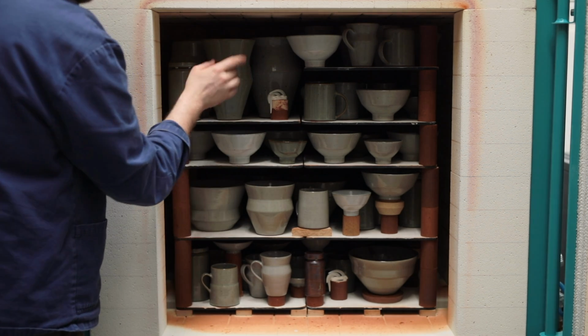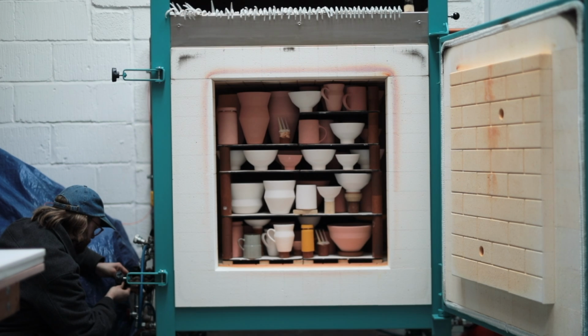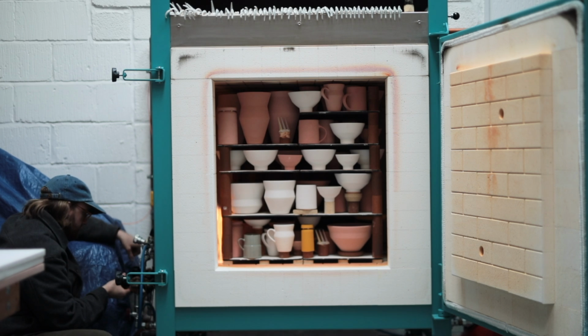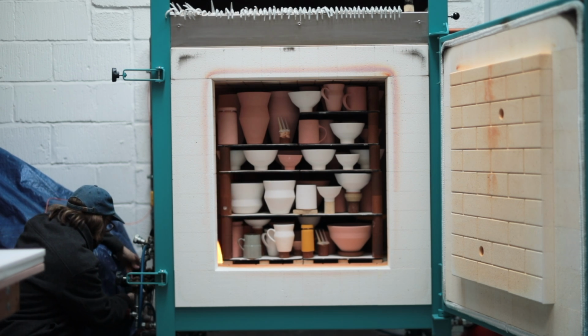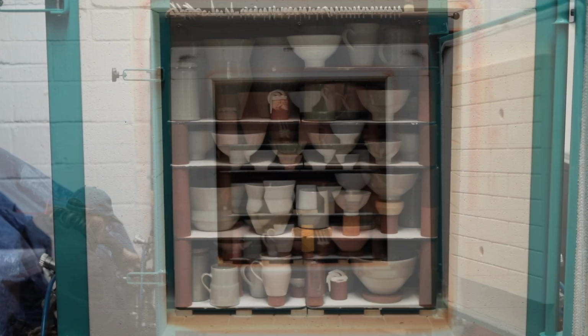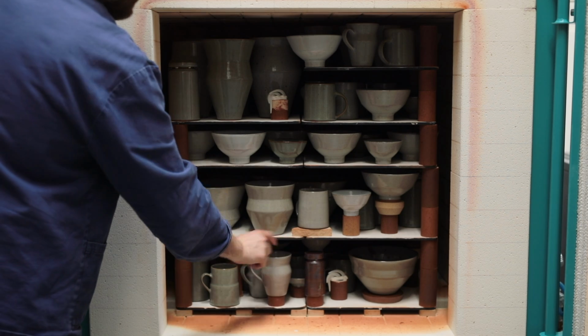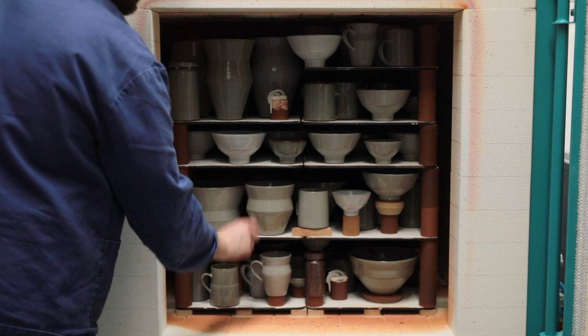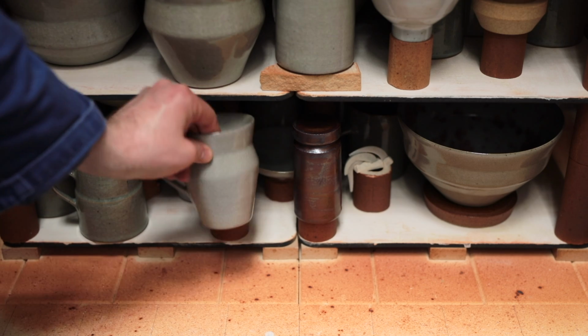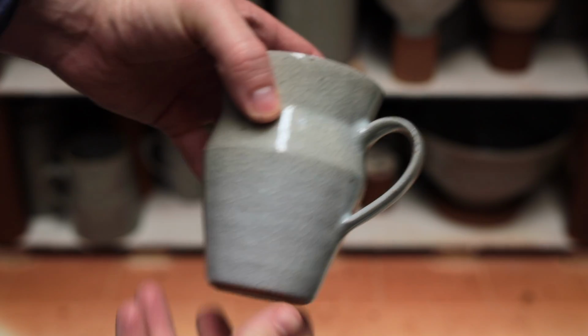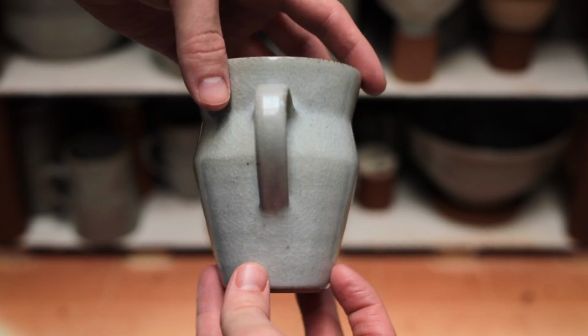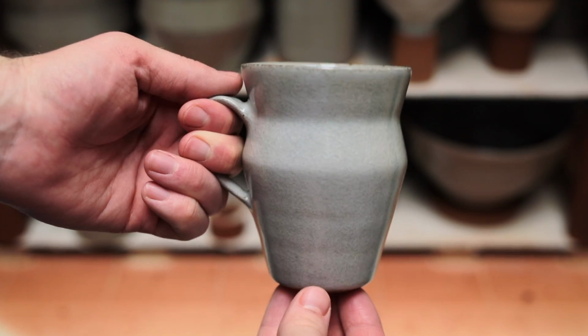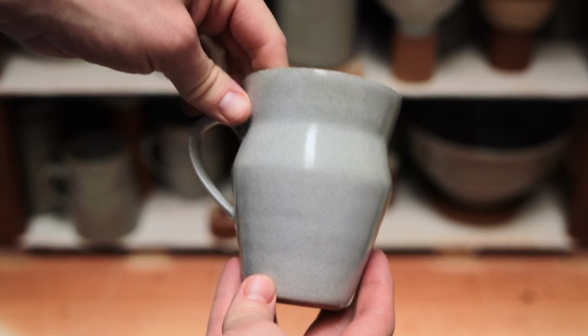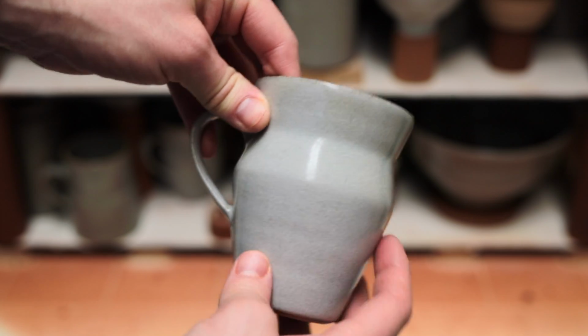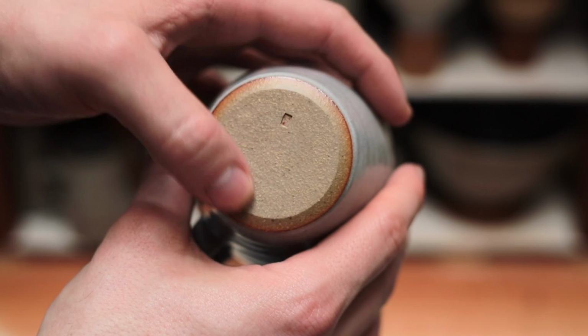There being cool spots at the bottom is why I often place refires on this lowest layer, such as the yellow jar you can see here, coated in yellow ochre iron oxide, or the pale green mug on the far left. As pots placed here often don't fire very well, I normally just save it for refires. And that matte quality pots sometimes have looks a little bit like this, meaning this angular mug will most definitely be fired again. And even if it's placed in the exact same spot, a second dose of heat will make this surface glassier and more interesting.